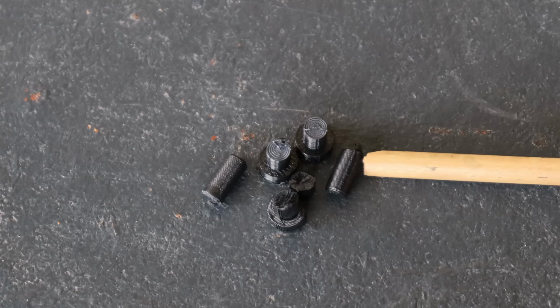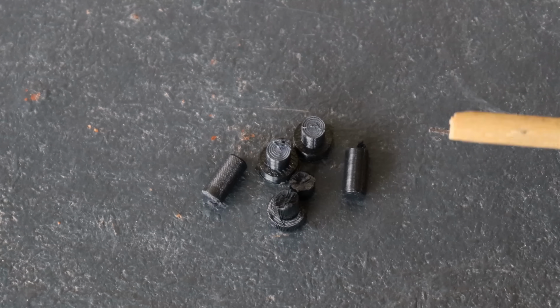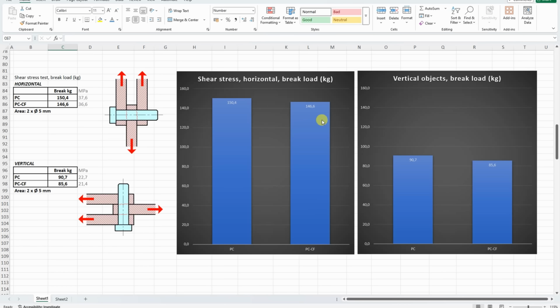Now I thought that the polycarbonate would be slightly stronger than the regular version, but the difference is not big anyway. On the shear test, interesting that the carbon fiber didn't help with the horizontally printed test object, and with the vertically printed, where the layer adhesion is important, again the regular polycarbonate was slightly stronger compared to the carbon fiber version.